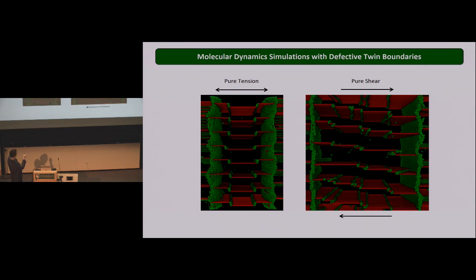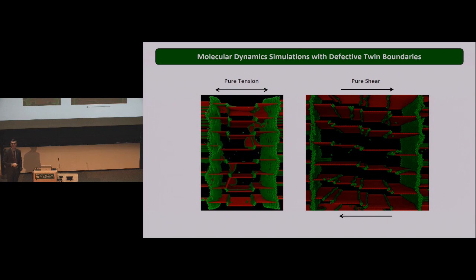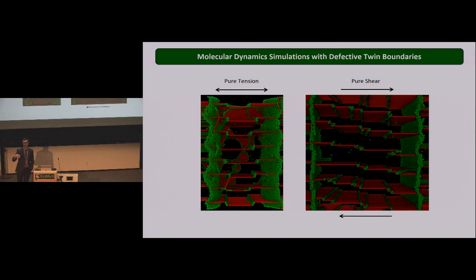So in this one, we have a film, and we pull in this direction. You have a twin boundary here. There's a defect here. It's a kink. And then we have two grain boundaries here. What you will see is a dislocation that tries to nucleate, another one here. And then at some point they're going to travel. But when they travel, they leave some debris. Those defects actually bind those dislocations at different locations, right? And then it becomes very complicated. Even some defects start to move, migrate, even though we never applied any shear to it. So it's a much more complex picture of the deformation mechanism as soon as you introduce very tiny defects to